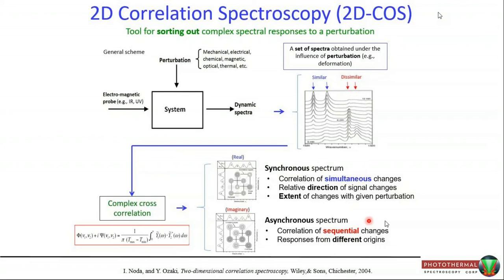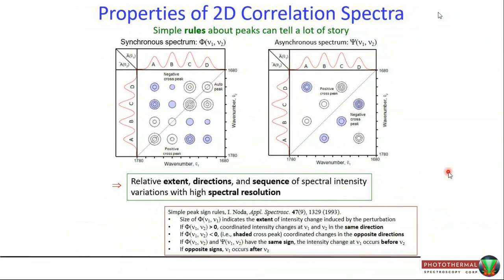The properties are listed here. Synchronous spectrum is a symmetric map. You see the peaks located at diagonal position. If the intensity of particular band changes very strongly, there's going to be very strong peak appearing at the diagonal part, that is called autopeaks. If the intensity of particular band does not change much, then their peak intensity becomes very small.